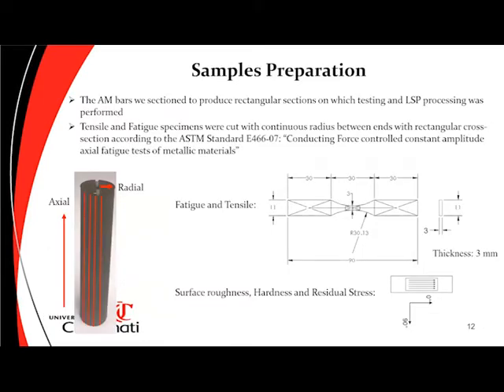Now explaining a bit about the sample preparation. The cylindrical blocks were sliced into rectangular strips using the EDM. These samples were then polished, and after that, laser peened with the set conditions. The samples were then EDM cut to shape for the tensile and fatigue test based on the ASTM standard as shown in this figure.